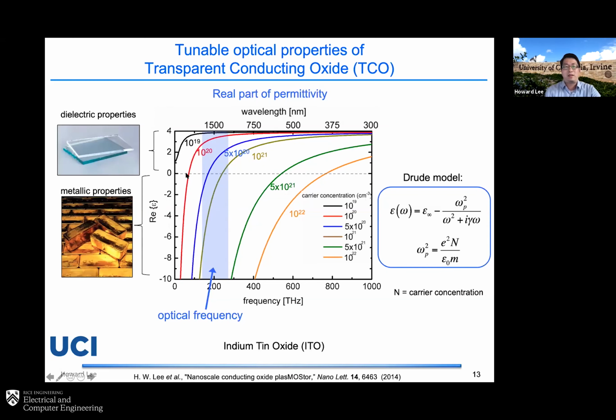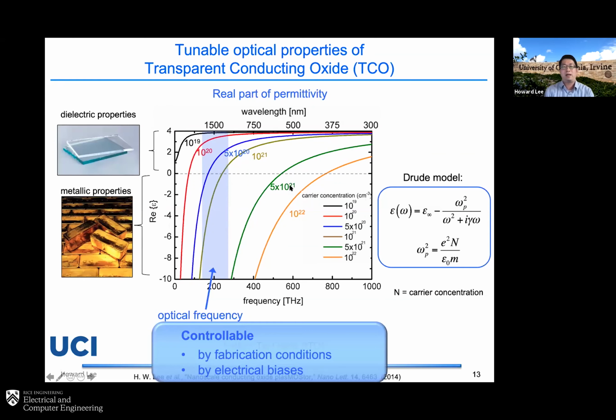And other than that, if you look at the axis crossing point, we call this the ENZ point, you can shift the ENZ wavelength to the infrared or even close to the visible range, depending on the carrier concentration. So you can really tune this material by changing the carrier concentration, which can be done by the fabrication condition. When you fabricate a material with different conditions, you can have different carrier concentration. Or you can also electrically bias, gating the material, so that you can tune the optical property.